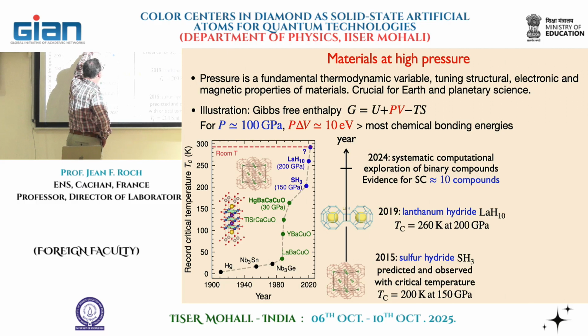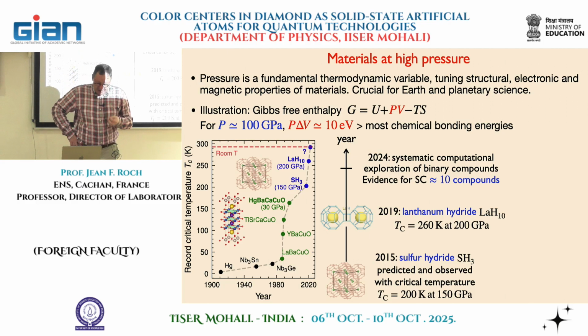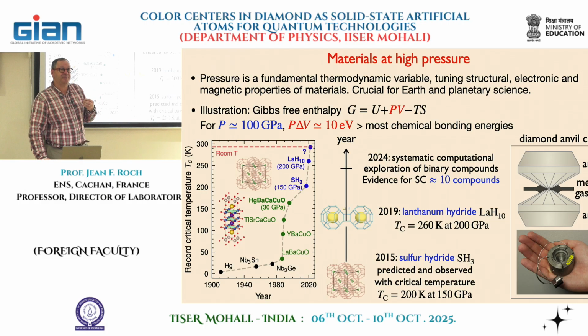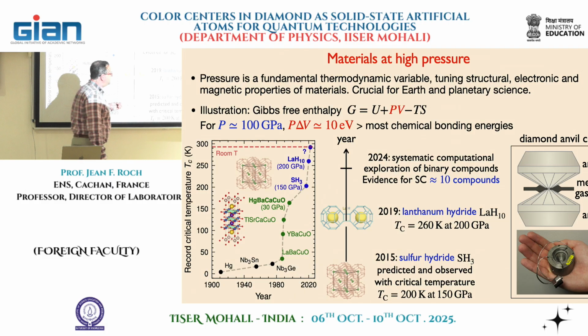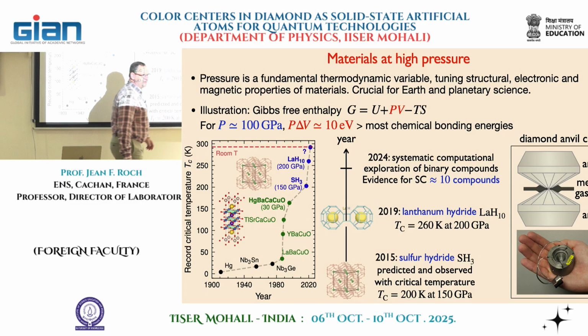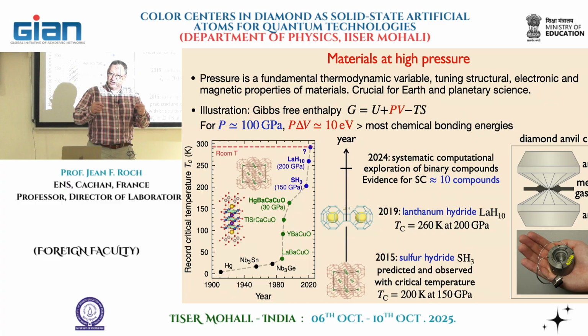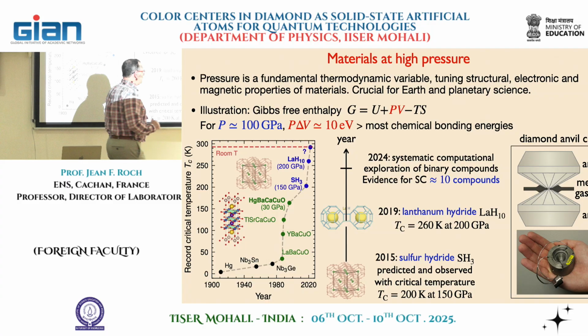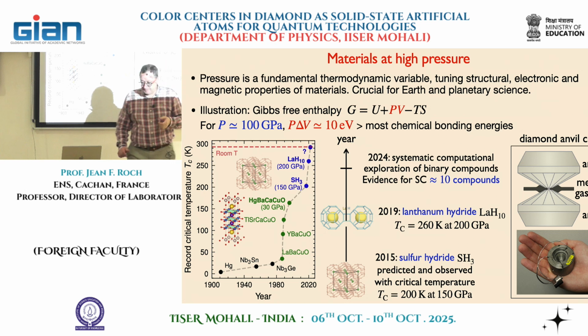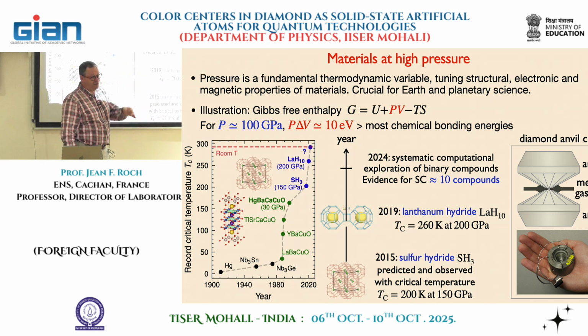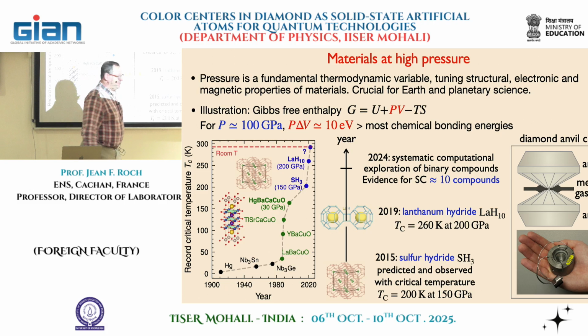So we would like now, again, to reproduce all these experiments at high pressure. And why do you want to do it? First, all these experiments are realized with this remarkably simple tool, the diamond anvil cell. The diamond anvil cell consists of two diamonds cut and shaped with a tip. The tip has a diameter that can go from 500 micrometers to a few micrometers. For instance, people who want to achieve 400 gigapascal will work with a diameter of the culet, the tip of the anvil, that will be around 20, even 10 micrometers. So you can imagine how small the system will be.